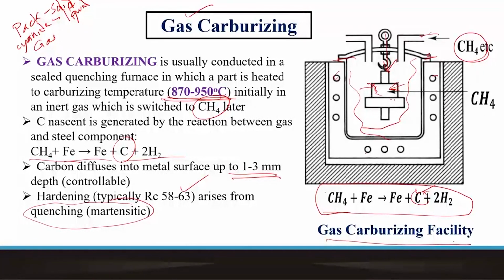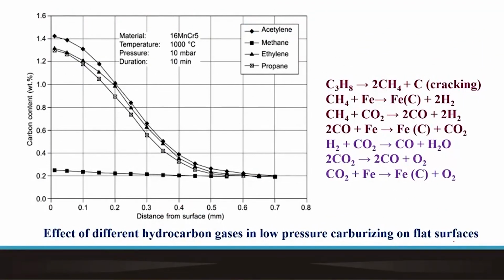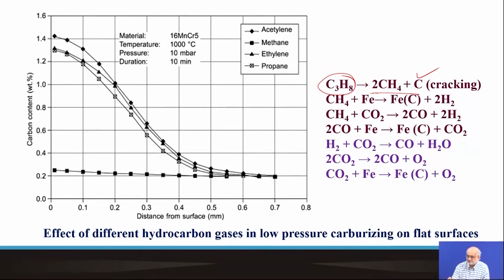So just like in the case of liquid bath or cyanide bath treatment, here we are dealing with a higher hydrocarbon, propane, and then we allow this to be dissociated. And during this dissociation process, methane forms. Along with that we also have carbon released, nascent carbon released, and that carbon gets adsorbed to the surface. We could also have a parallel reaction where methane reacts with carbon dioxide, forms carbon monoxide, and carbon monoxide in contact with the iron charge or the steel charge allows dissociation, release of carbon from carbon monoxide and carbon dioxide.